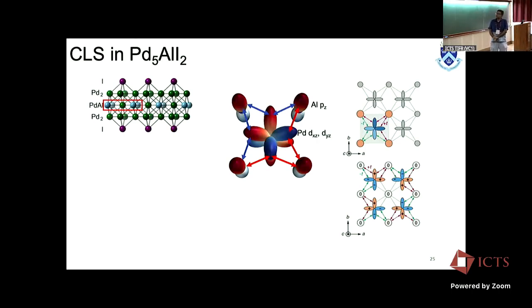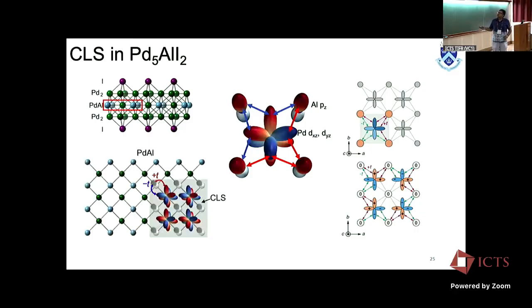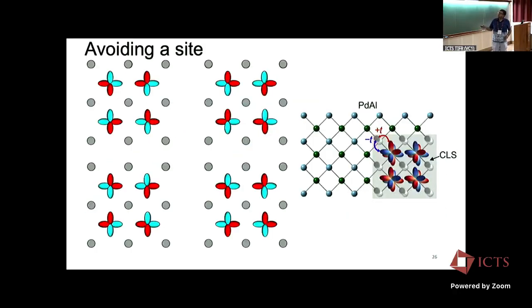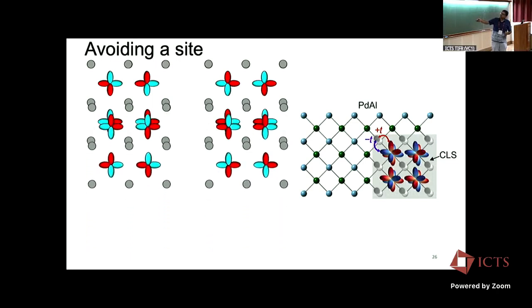And now I want to create a defect in this lattice. Now I have to avoid a site, as I told you, when I create a defect. And in order to do that, I have to take 4 of these compact localized states. So here is one, here is one, here is one, here is one. And pay attention to the relative phases of these 4 compact localized states. And if I superpose this one and this one, I add these together,